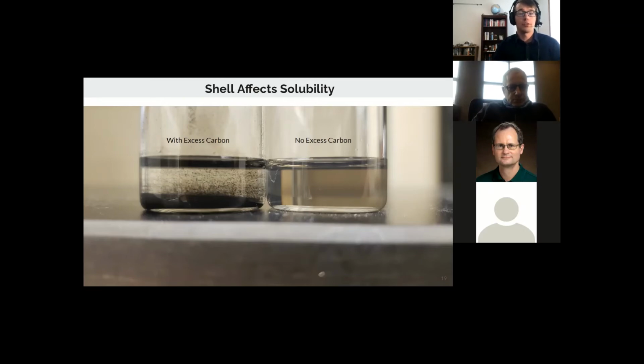So this image demonstrates the increased solubility of silicon carbide nanoparticles when the excess carbon is removed. The left vial contains a sample of unprocessed silicon carbide nanocrystals sonicated in isopropyl alcohol for 4 hours. The right vial contains a sample of nanocrystals after removing the excess carbon and then sonicating in isopropyl alcohol for 4 hours. So this photograph was taken after the two solutions had been left sedentary for several hours, and it's clear to see that the sample with excess carbon has aggregated and settled to the bottom of the vial, while the sample without as much excess carbon stayed in a uniform solution in isopropyl alcohol. So now the question is, how do you remove excess carbon from the nanocrystal while leaving the underlying core the same?